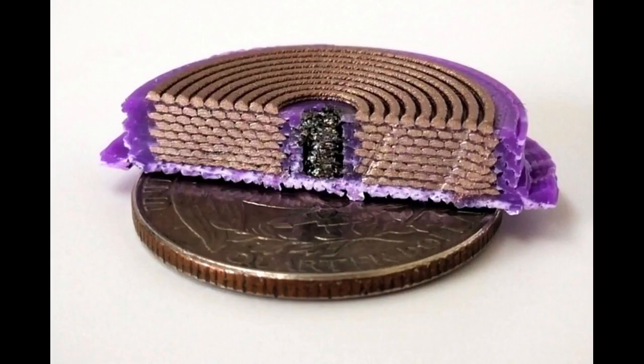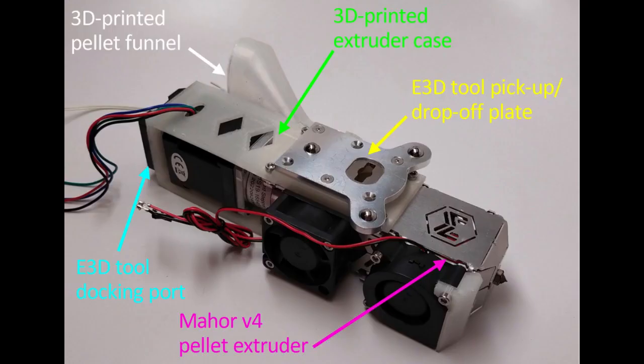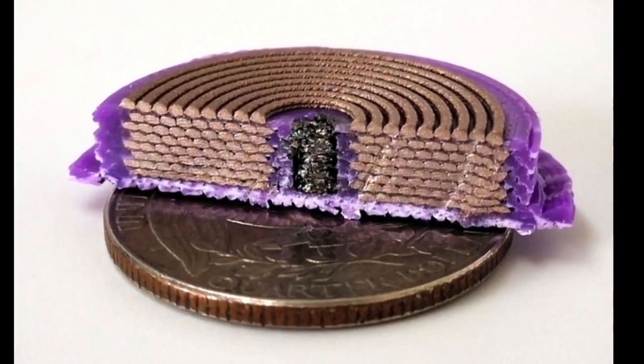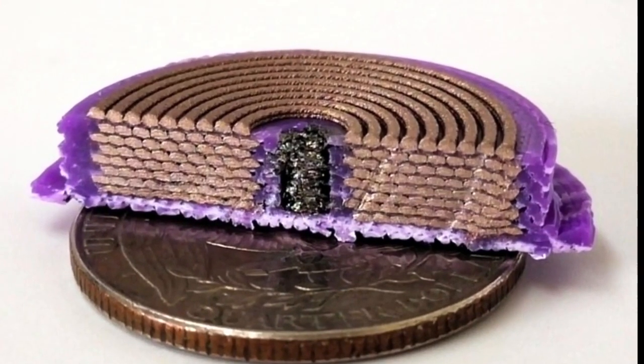The researchers modified a multi-material 3D printer so it could print compact magnetic cored solenoids in one step. This eliminates defects that might be introduced during post-assembly processes. This customized printer, which could utilize higher performing materials than typical commercial printers, enabled the researchers to produce solenoids that could withstand twice as much electric current and generate a magnetic field that was 3 times larger than other 3D printed devices.